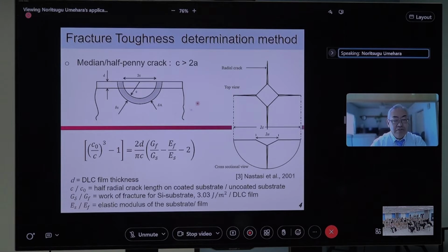So consider the fracture toughness or the stress intensity factors. We are considering it in the following way: the crack length is C. If this crack length is expanded up to delta C like that, this gray shadowed part is the crack propagation area. In order to get crack propagation, of course, we need new energy. If this new energy is small, its fracture toughness is quite low. If this new energy for making the new crack surface is high, its fracture toughness is quite large.